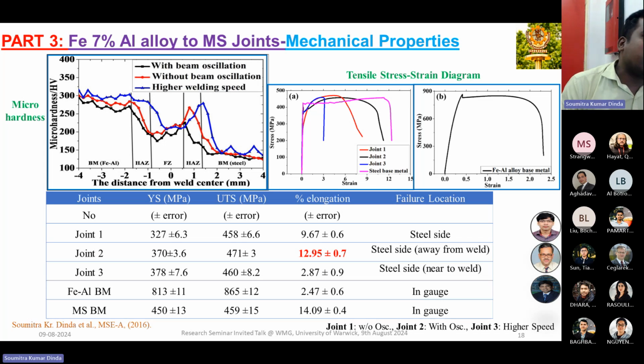Now, if you compare all three joint conditions, joint 1, 2, and 3, we can see that the YS, the yield stress, and the UTS, the ultimate tensile stress, are not changing that much. It's quite similar. But check the elongation. In case of joint 2, we got elongation near 13%, compared to 9.6 for joint 1, and joint 3 is 2.8, the lowest one. So in case of joint 2, the elongation is maximum and very close to our steel base metal.